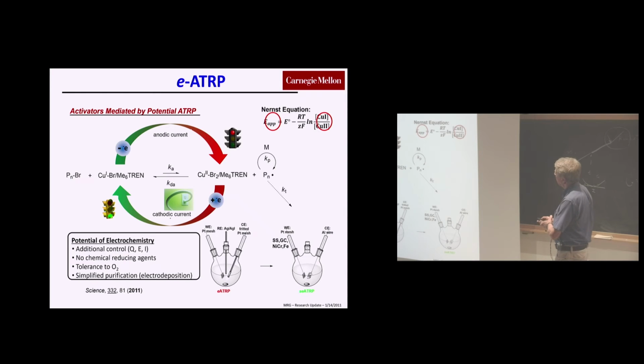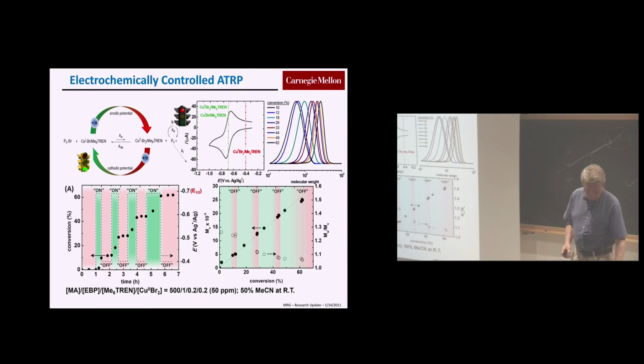If you look at the principle of electrochemistry, the applied potential should control the ratio of copper 1 to copper 2, which means it would control the amount of radicals. If I have more copper 1, I have more radicals. If I have more copper 2, I stop the reaction. So by changing potential, I can control the rate of the reaction pretty precisely. So here's an example. If you take the cyclic voltammogram of this copper complex, if I am at sufficiently positive potential, there is no electron flow, so there is no polymerization, the reaction stops. If I go to more and more negative potential, then I generate more and more activators, and polymerization would start, and then I can go back.